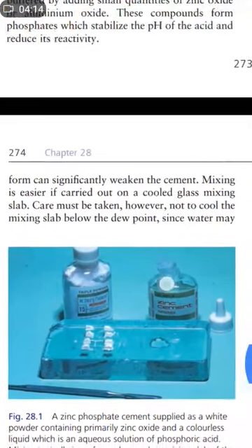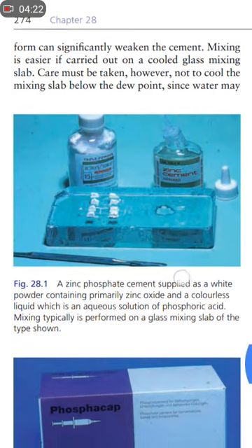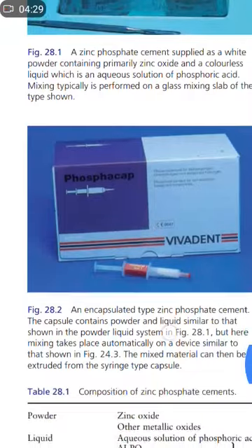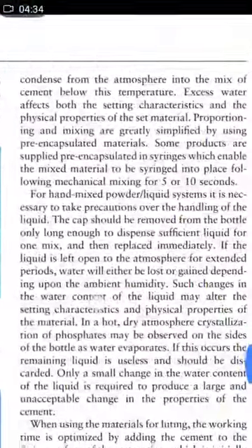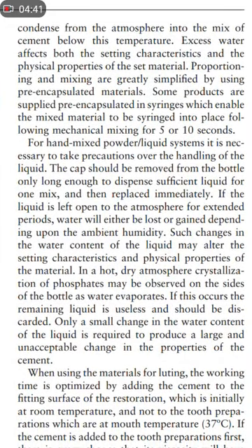Mixing is easier if carried out on a cooled glass mixing slab. Care must be taken, however, not to cool the mixing slab below the dew point, since water may condense from the atmosphere into the cement mix below this temperature. Excess water affects both the setting characteristics and physical properties of the set material. Proportioning and mixing are greatly simplified by using pre-encapsulated materials. Some products are supplied